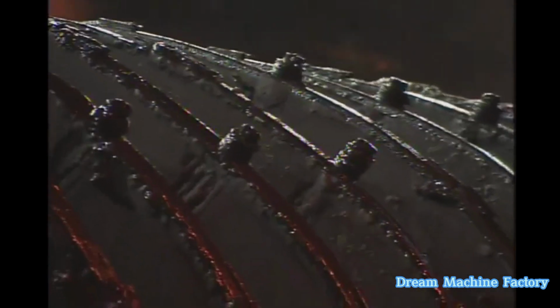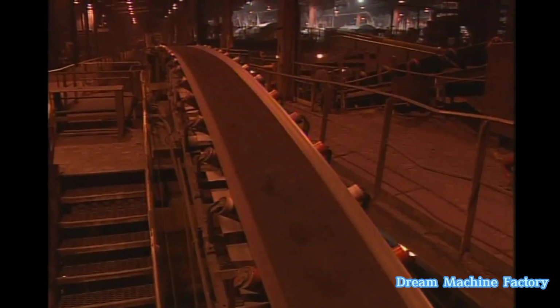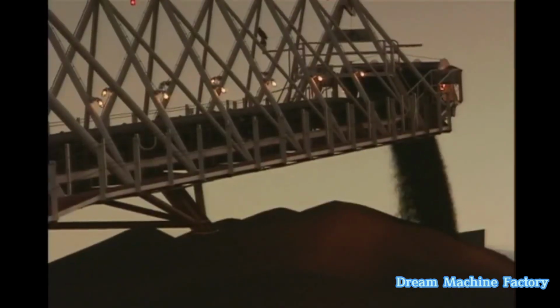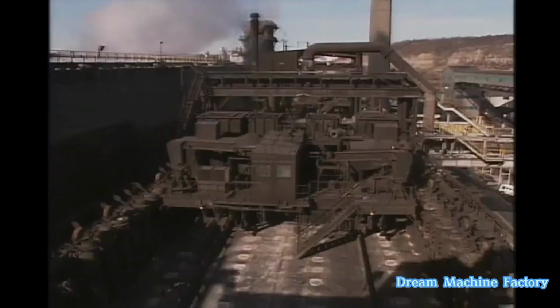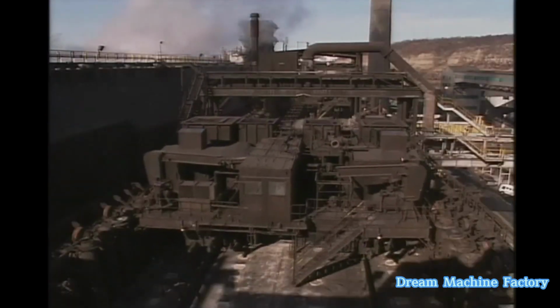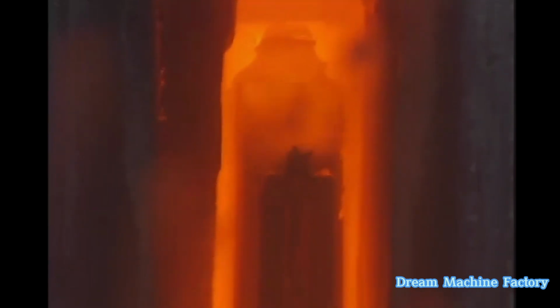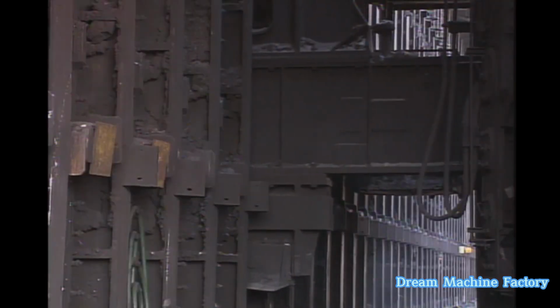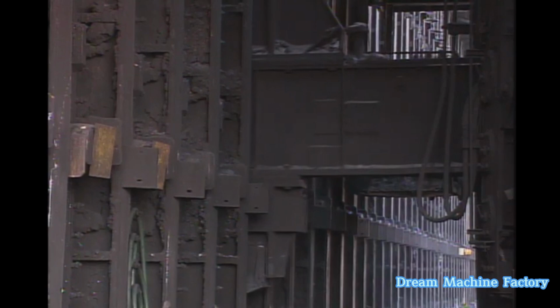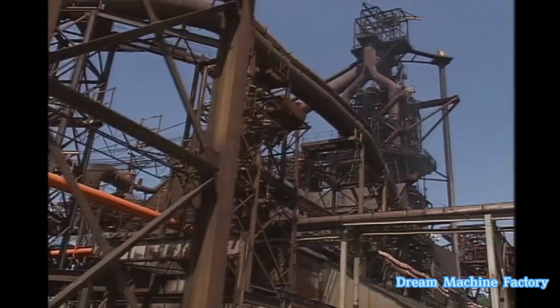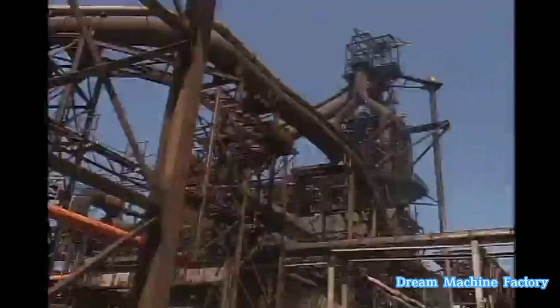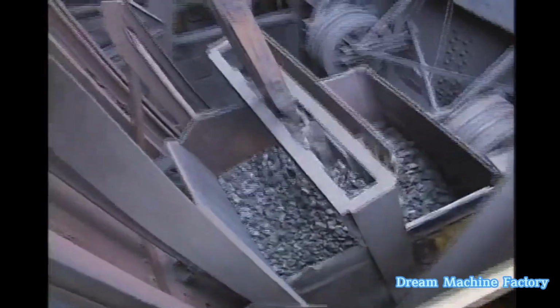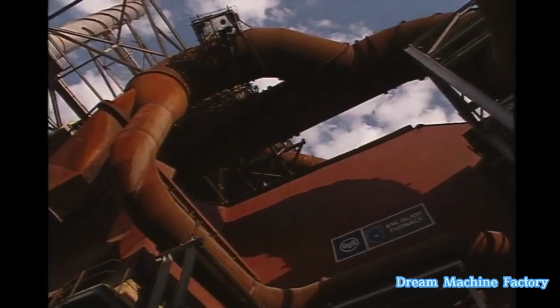The next stage occurs in the blast furnace, where iron ore pellets, coke, and limestone, used to remove impurities, are combined. A continuous blast of superheated air ignites the coke, creating intense heat to convert the raw materials into molten iron. Temperatures inside the blast furnace can reach a staggering 2,700 degrees Fahrenheit. In large furnaces, over 90,000 tons of molten iron can be produced daily.